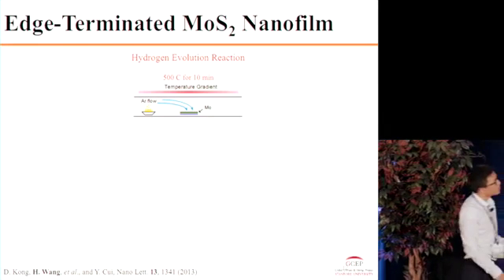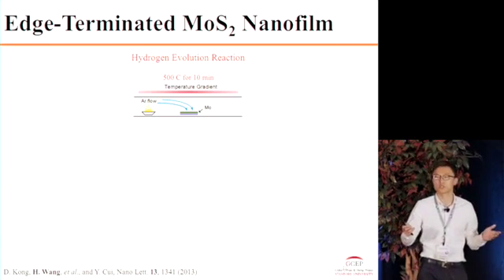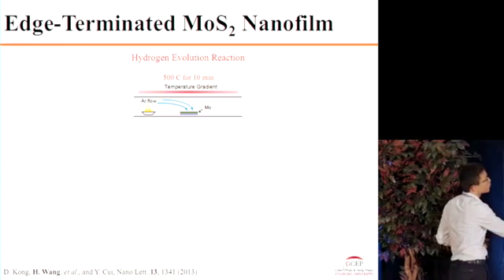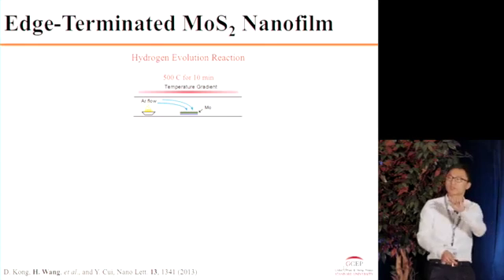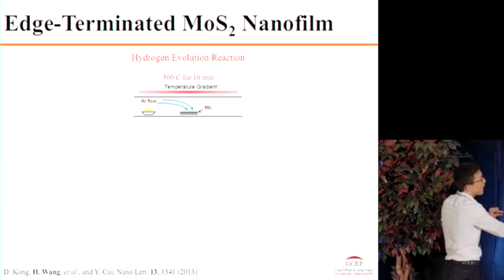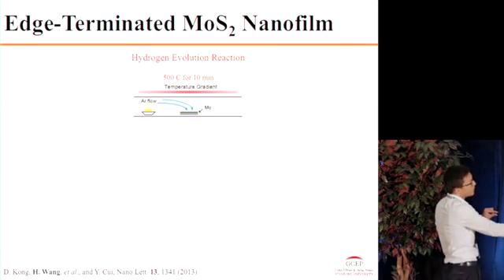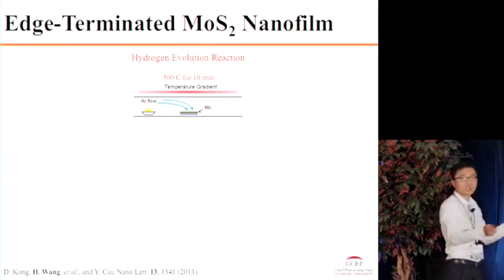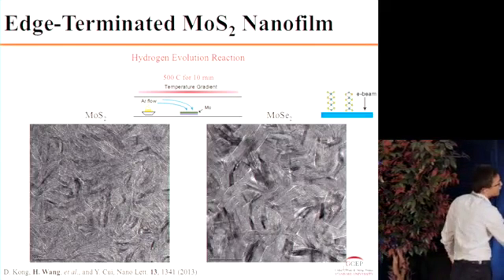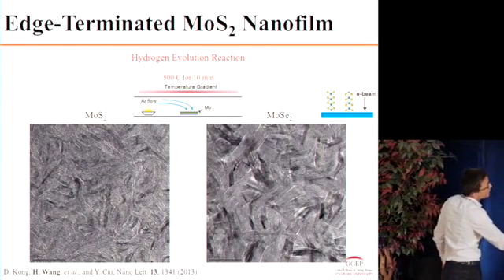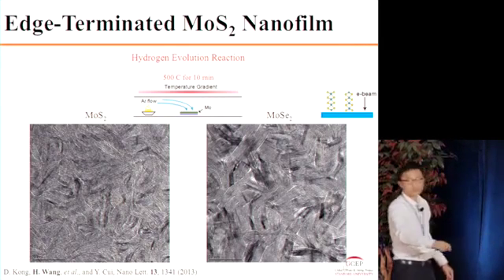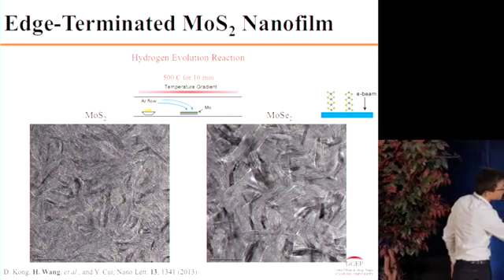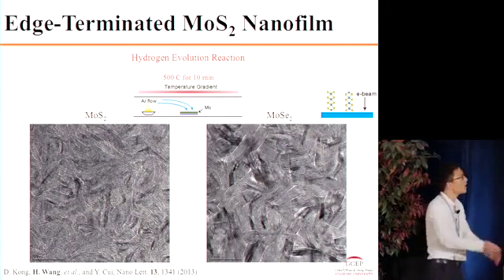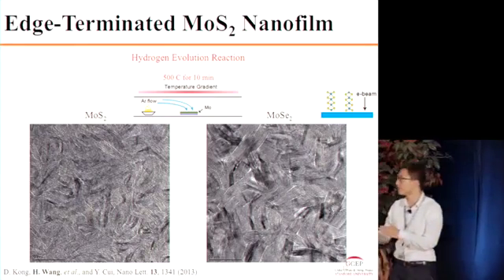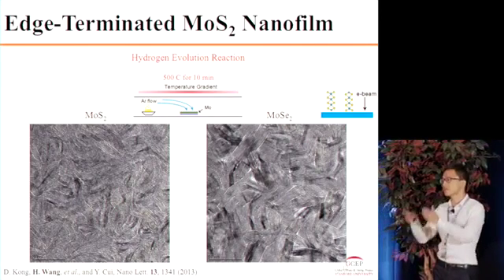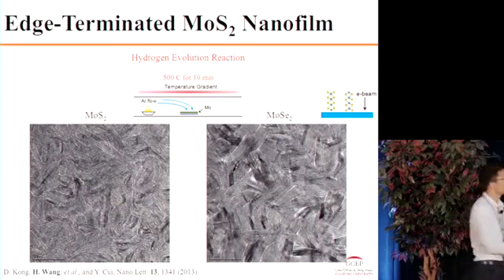The way we want to achieve that is through chemical vapor deposition at high temperature. As we can see, we have a molybdenum thin film deposited on the substrate, and we evaporate sulfur and react it with the molybdenum in a hot zone within a very short time. And as we can see from the TEM image, the electron beam is perpendicular to the screen. You can see a lot of gaps, that is van der Waals gaps, facing us, which demonstrates that the structure is layers vertically standing on the substrate.